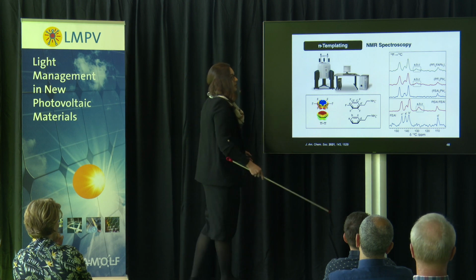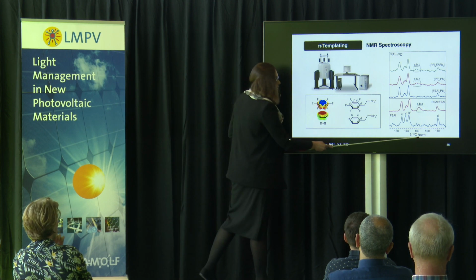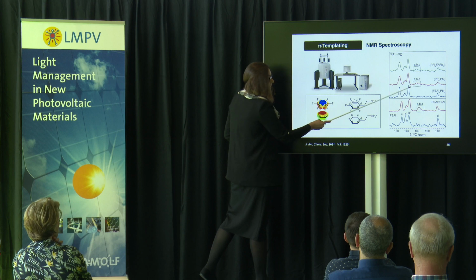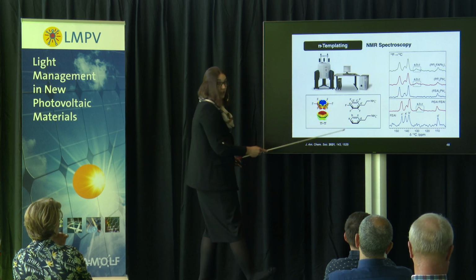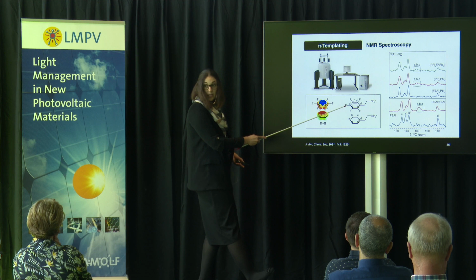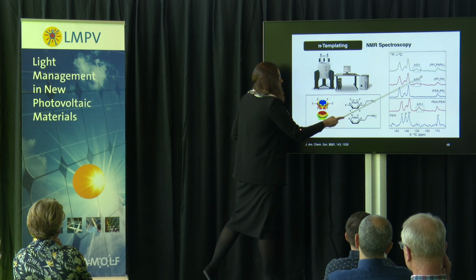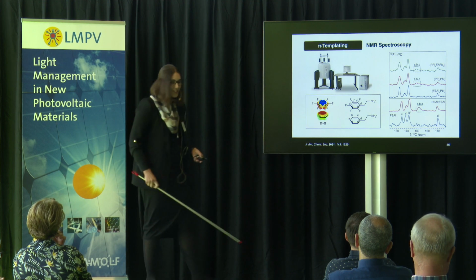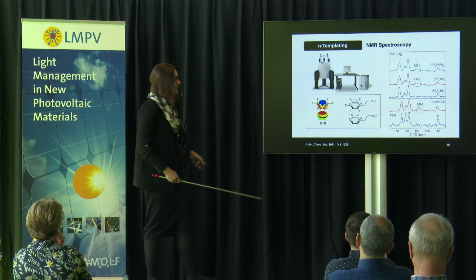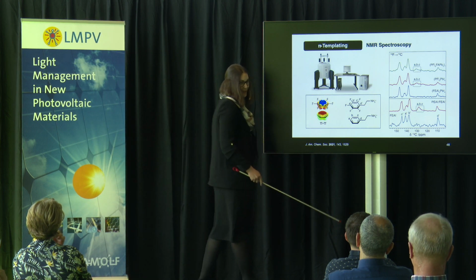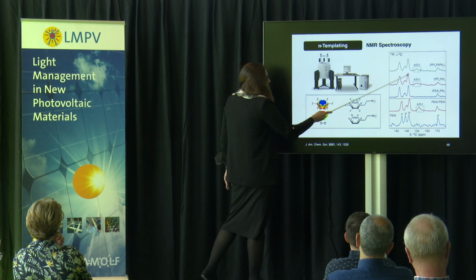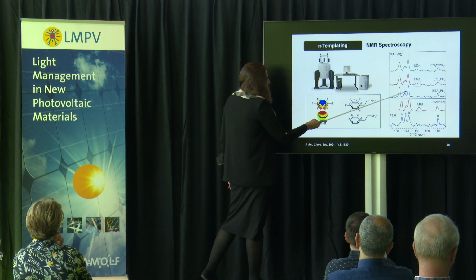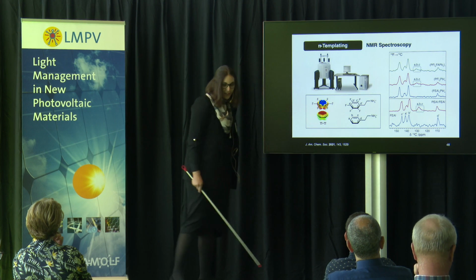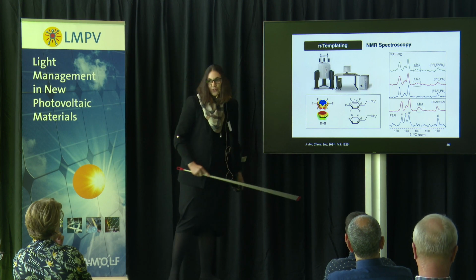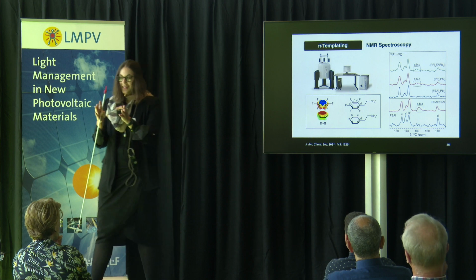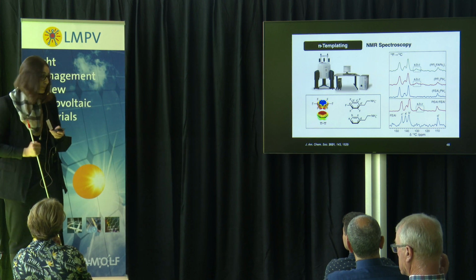And as a result, we can observe the presence of additional signals in the corresponding NMR spectra that can be associated with some of these exchanges in both the mixtures of the neat organic components as well as the hybrid perovskites. However, this example opens another question: do we really understand these structures? When we look at the other spectral characteristics, we can see that they're fairly comparable, which makes us ask ourselves, is this nanoscale proximity really the result of forming the desired supramolecular assembly?